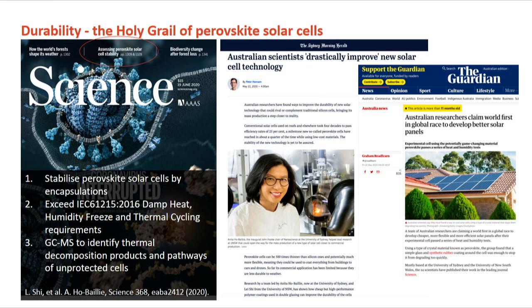The encapsulation technique that we use has to be low temperature as well, because perovskite doesn't like high temperature. And we use a technique that is commonly used for double glazing. So we managed to get the cells to pass the stringent IEC testing standards, long hours of damp heat, a lot of thermal cycling. We make it really hot, make it really cold, and then introduce water crystals as well, see if we can introduce it into the cell, and then freeze it.